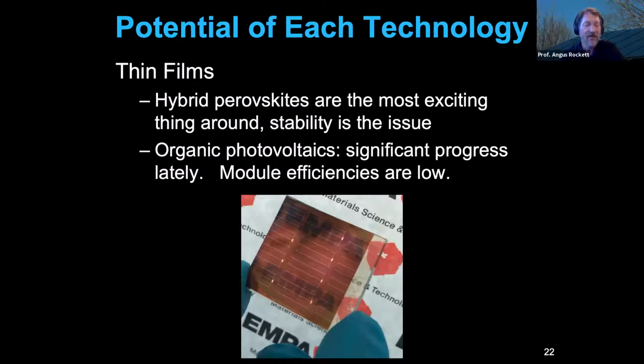Organic photovoltaics have always faced challenges. In particular, so-called exciton binding energies: the free negative charges and the free positive charges tend to stick to each other too well in organic materials because their dielectric constants are relatively low. And so that's been a challenge, but there have been some really exciting developments in organic photovoltaics lately. The modules remain relatively low efficiency, but there's still opportunities for improvement there. So that's a quick tour of some of the major technologies.